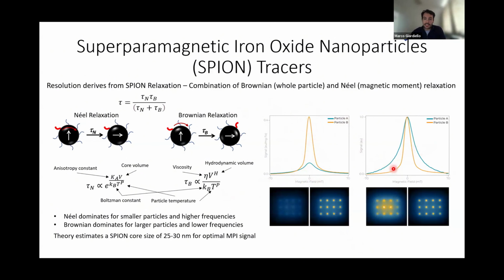On the right-hand side, how you interpret resolution is to normalize these two curves and look at the width of the curve at the full width half maximum. Here you can see the wider it is, the less resolved, and you can see that in the images that you have here. Although, particle A, sorry, I got it the wrong way around. Particle A is the least sensitive and less resolved, and you can see that in the images at the bottom. So it's a combination of Brownian and Néel relaxation.